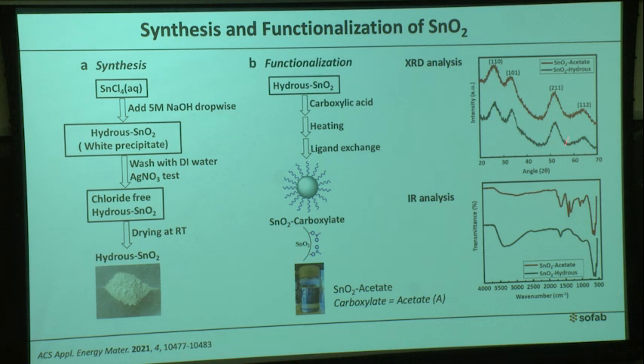But it doesn't tell the whole story, so after that we characterized it using IR. The peak present around 650 is related to the tin-oxygen bond in tin oxide. After functionalization, in this clear tin oxide solution, there is no change in peak position, so we can say this clear tin oxide solution still has the same tin oxide present, but in a different form.